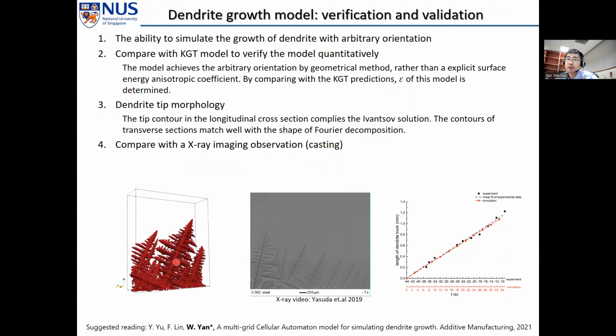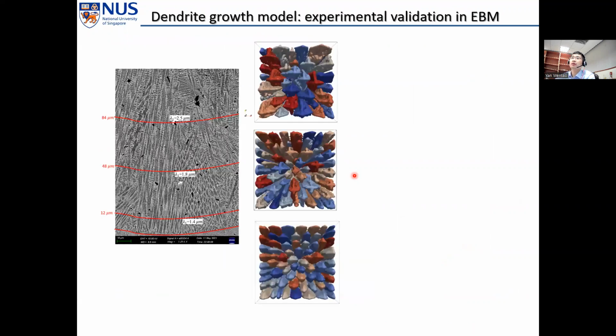This is a simulation result, and this is an X-ray imaging observation. And also this is a dendrite growth rate. But this is still insufficient for validation because in casting, the cooling rate and temperature gradient are much smaller than those in additive manufacturing. So we further validate our model against the electron beam additive manufacturing experiments. And in different locations, the cooling rate and temperature gradients are different.